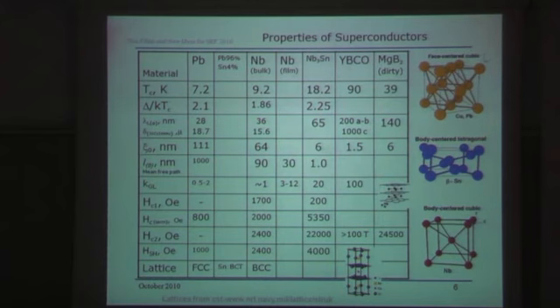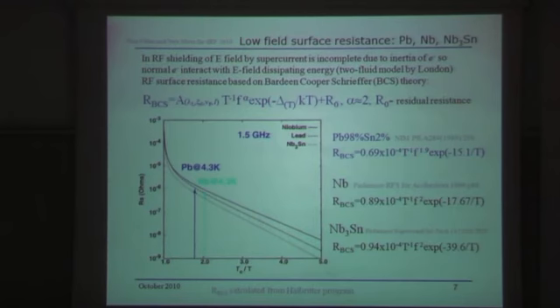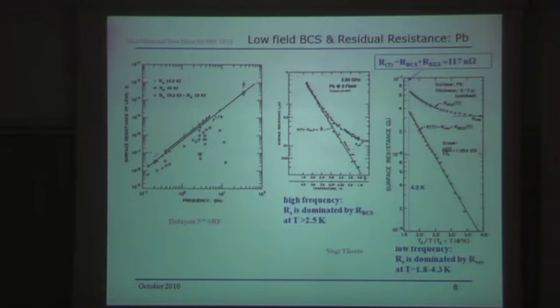So let me just skip all the slides because we already had excellent theoretical confirmation. But here we just want to point out that lead can have quite similar surface resistance as niobium. As we know, for low frequency applications, surface resistance is dominated by residual resistance in this material, so we don't have to go to low frequencies. We'll just mention that we have this range of resistance in nano-ohms based on experience from ALPI and Argonne National Lab results for low frequency cavities.